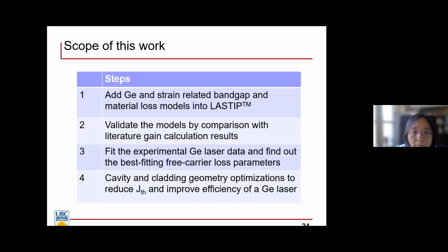And basically, we need to add germanium and strain-related band gap and material loss models into a commercial simulation tool called LASTIP. And we need to validate our models with experimental data. And then from that, we can find out what if we do all these optimizations, for example, the cavity and cladding geometry, and we can also put in some better material parameters to see how much better the germanium laser performance can be. So that's the scope.